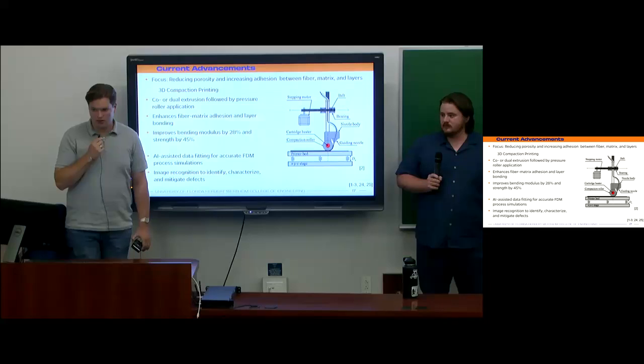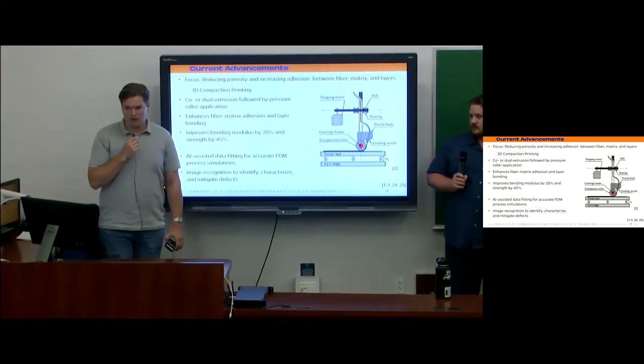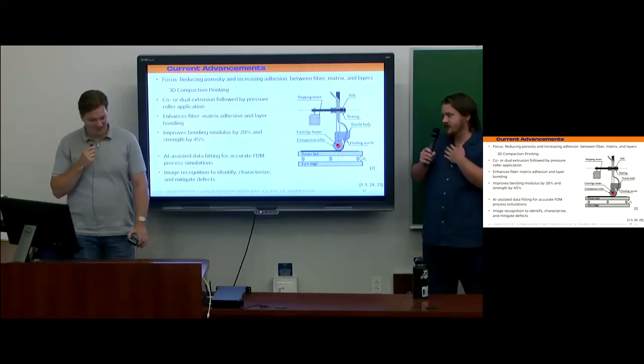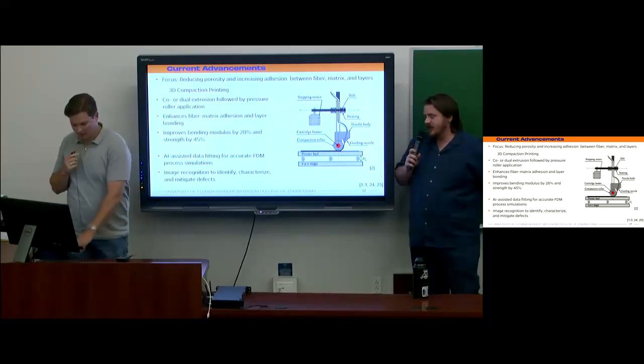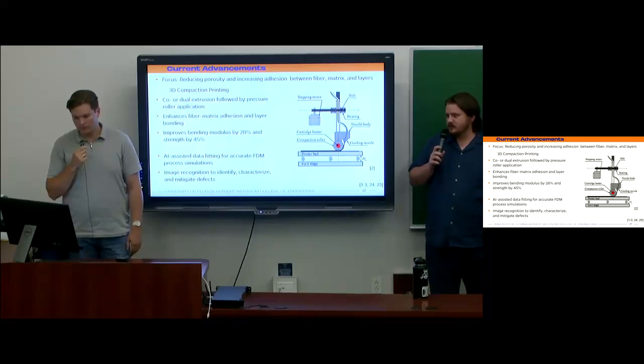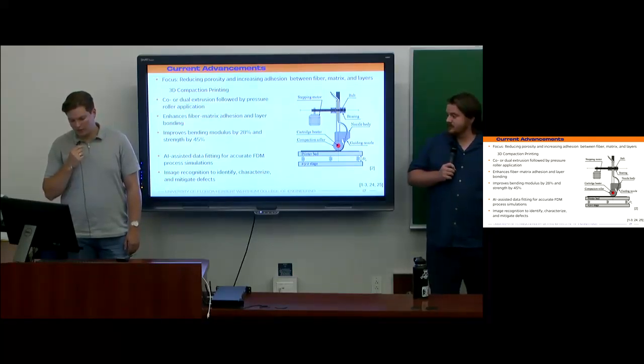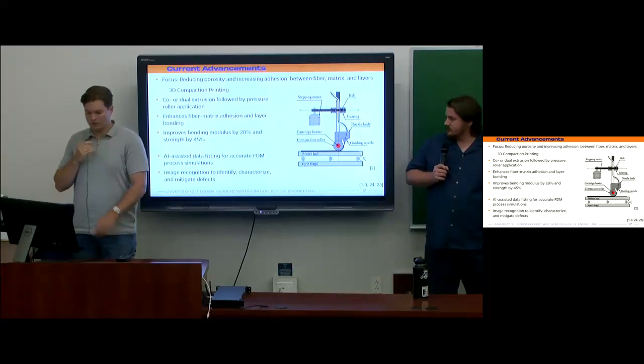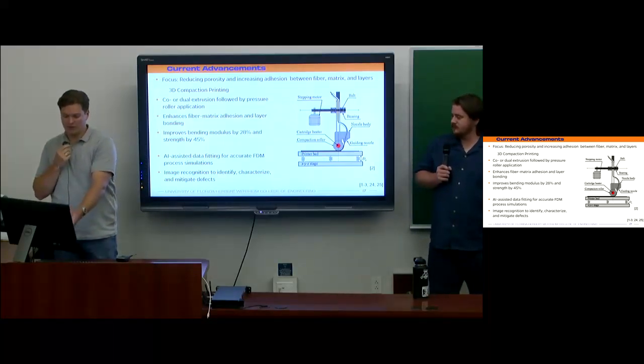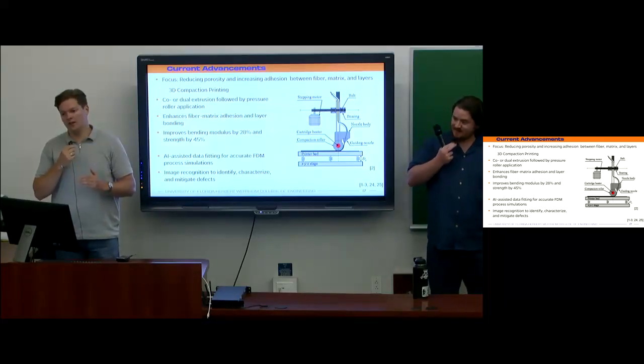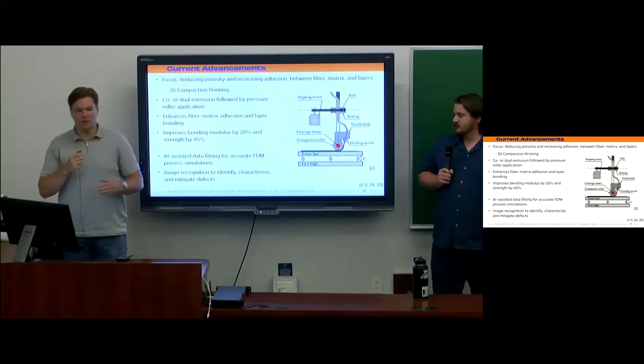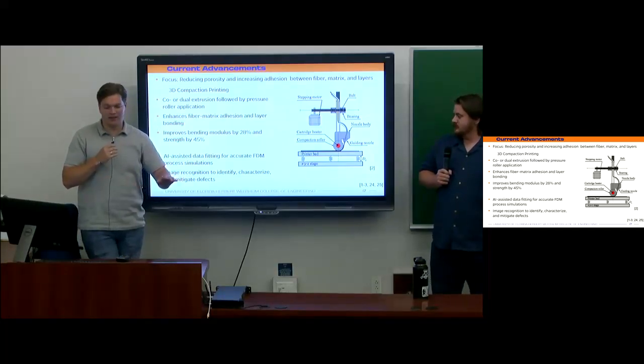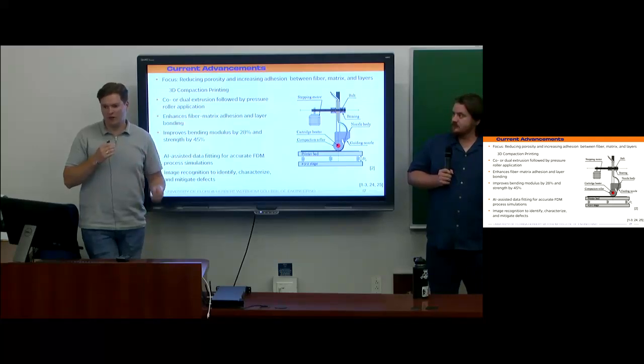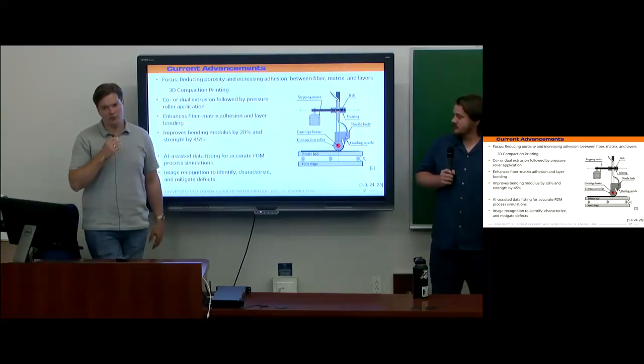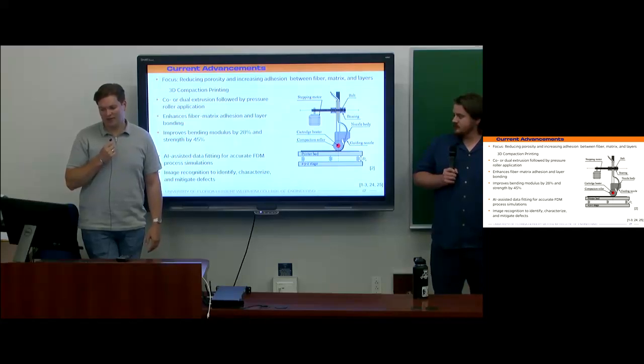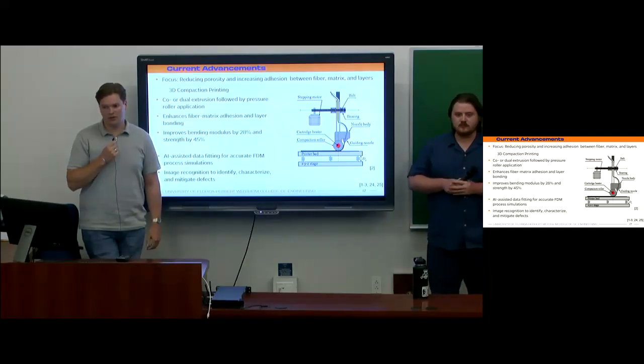How does the strength compare to traditional carbon fiber layers and such? It's a lot lower. We showed the improvement through the bending modulus and the strength. Traditional fiber, not that traditional 3D printing. Oh, I don't think we had a number for that in here. But yes, this compaction printing improves the bending modulus by 20% and the strength by 45%, but it was still lower than, for example, a resin transfer molding process, because there the continuous fibers can just be laid in the mold and they don't get damaged at all. And then the wetting is also a lot better because there are higher pressures involved. So yes, the 3D printing process cannot reach these mechanical properties.